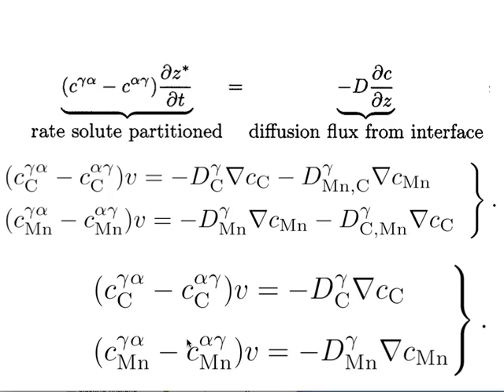In these equations, we compensated for the large diffusion coefficient of carbon by making the gradient flat. Is there any other method? If you focus on this term, if I want to increase the flux of manganese, then I should make the gradient steep, right? So how do we make the gradient steep? Now, suppose we wanted to make the concentration gradient of manganese steep. And if I just sketch out the concentration gradient, so this is C bar, this is C gamma alpha, C alpha gamma, and this is ferrite and austenite. So I want to make this gradient steep.